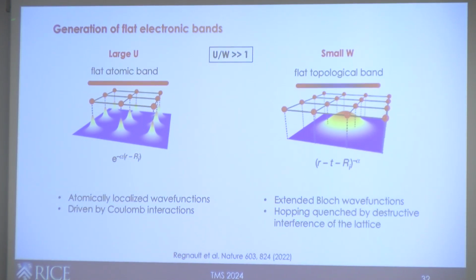So that's an example on the left-hand side. This is what happens when you have a Coulomb interaction-driven flat band. It's renormalized to the Fermi level, spectral weight goes away, and I'm going to want to contrast that with the right-hand side, which is the kind of flat band you get by quenching out W.